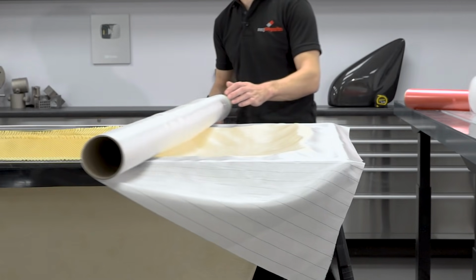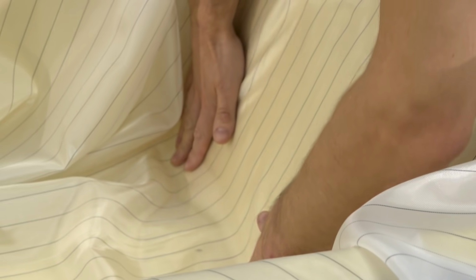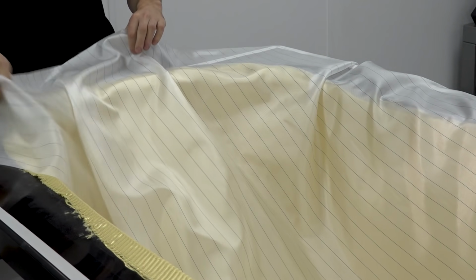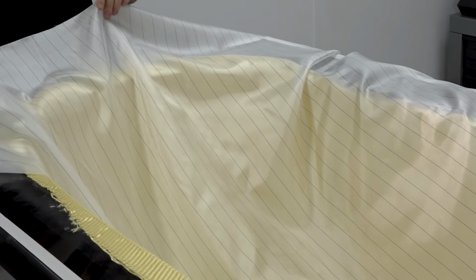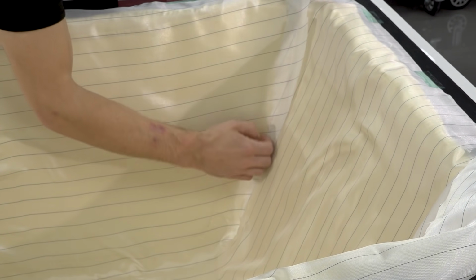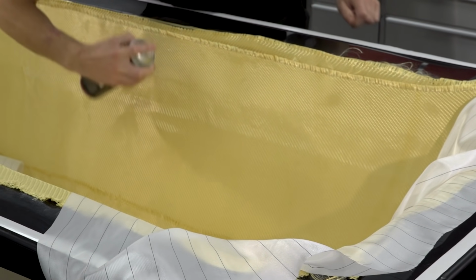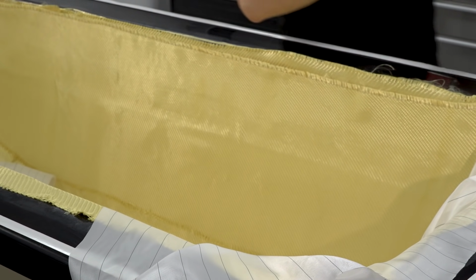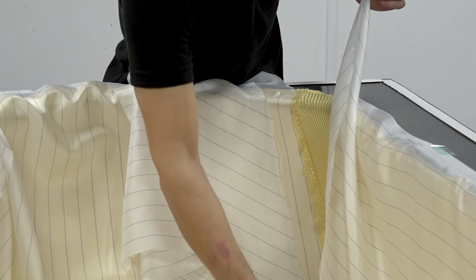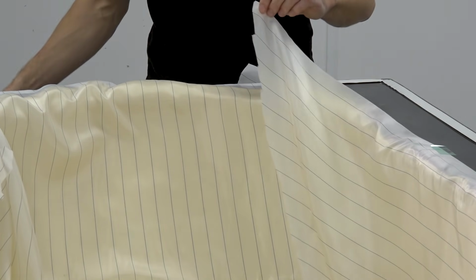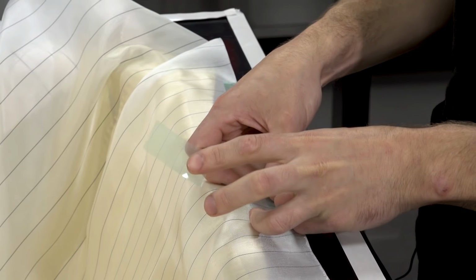The peel ply is now laid into the mould. In many ways this is a very similar process to laying the reinforcement. Whilst overlaps and joins in the peel ply are absolutely no problem, gaps would be. So you must ensure you have complete coverage. Spray tack can be used to position the peel ply if necessary. The peel ply should be sized slightly larger than the underlying reinforcement and secured to the flange using flash release tape.